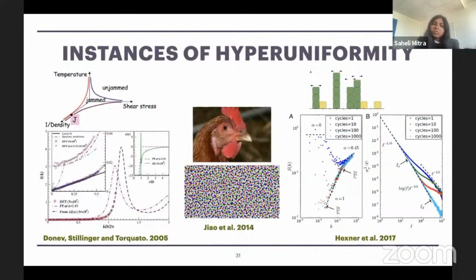For the last 2 decades, hyperuniformity has been found in lots of systems. Here, I am only presenting 3 such examples. On the left, I have a system of jammed particles, in which case it was found that at critical jamming density, the structure factor tends to vanish linearly close to the origin. And later, upon many explorations, it was conjectured that all maximally randomly jammed sphere packings will be hyperuniform in nature.